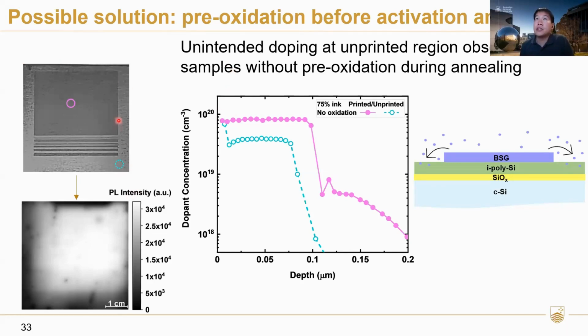Firstly, this is a sample that has been annealed without the pre-oxidation. If we measure the area that has been printed, we get this solid line here, which is quite normal. But if we measure the ECV at the non-printed area, we actually start to detect a signal as well. It's a bit lower, but it is there. We think that what's happening is that the boron from the boron glass is diffusing out into the non-printed area. In this case it's for boron doping, but we've also seen similar effects for phosphorus doping.